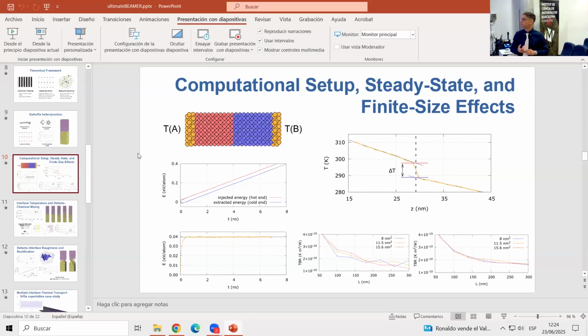I would say yes, because in fact, when you are close to the ballistic regime, you would really observe just side A at one temperature, side B at another temperature. So of course, the temperature drop at the interface would basically be the temperature drop that you would have at the thermostatic zone. So yeah, of course, I haven't thought about it yet.